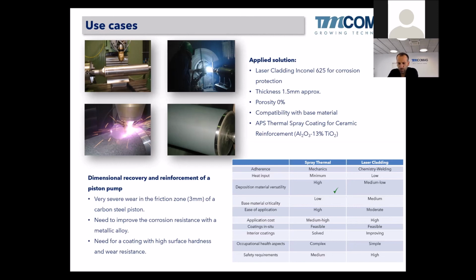So we had to improve the corrosion resistance of the pistons together with the wear resistance of the piston. So we chose a combination of both processes. We applied Inconel 625 to improve the corrosion resistance of the carbon steel piston, and then we machined the Inconel to a certain thickness to be able to apply an APS alumina-titania coating by plasma.